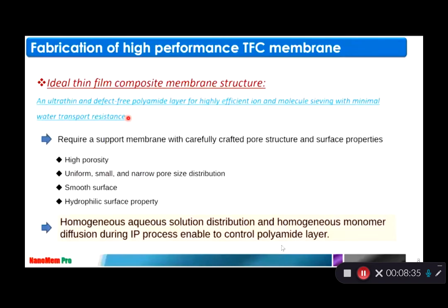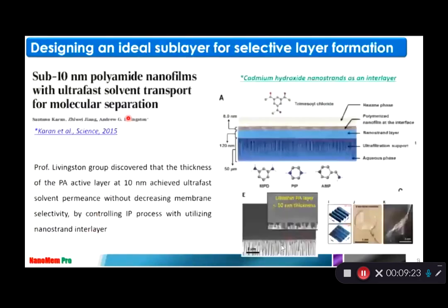publication. So the ideal thin-film composite membrane structure is very ultra thin, with a defect-free selective layer for highly efficient ion and molecular sieving with minimal water transport resistance. It requires a support membrane with carefully crafted pore structure and surface properties: high porosity, uniform, small and narrow pore size distribution, smooth surface, and hydrophilic surface property, which will lead to homogeneous aqueous solution distribution and homogeneous monomer diffusion during the IP process, enabling control of the polyamide layer. So we looked at the previous literature, and we found one interesting paper published in the very high